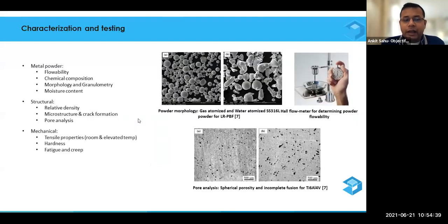Then, what kind of testing is required in the development of these alloys? When an incoming powder arrives at our facility, we test for flowability, chemical composition, morphology, and particle size distribution. We also check the moisture content, because any kind of moisture is bad news for any kind of processing. Then, after checking this, we print certain small cubes where we check the relative density of the coupons developed at a certain parameter. Then we work on the microstructure, any crack formation, and any pores present during the 3D structure development of the coupons.